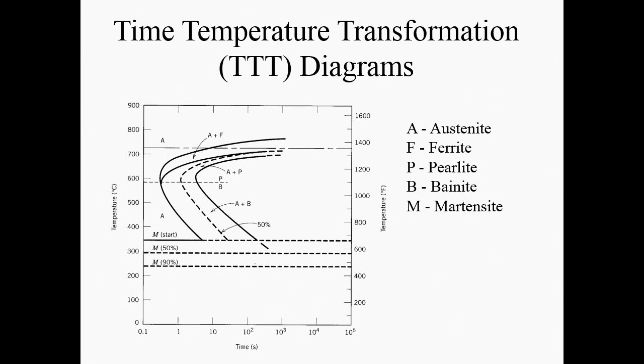So if you imagine this particular steel, this is a low carbon steel, if you heated it up to 900 degrees C and then quenched to 700 very, very rapidly and held it there, it would take about 1 second for phase transformations to start. So austenite is still stable here, and then we form some ferrite, and then we form some ferrite and pearlite, and it will be finished by the time we get to about here, 100 seconds. So we would get the thermodynamic stable material, which is in here, but we'd have to wait some period of time for doing it.